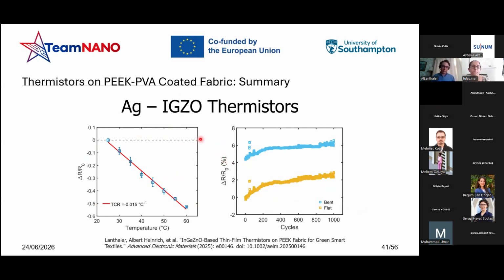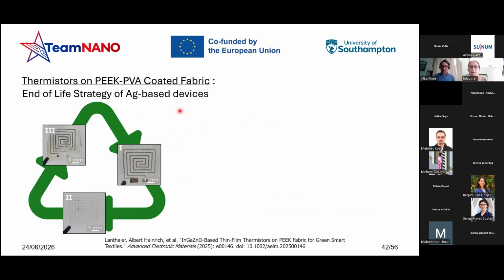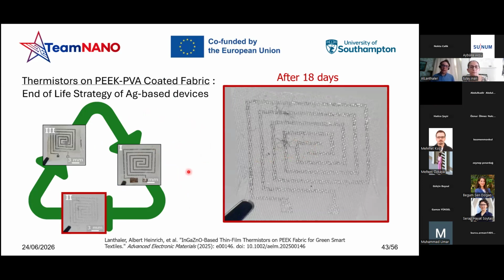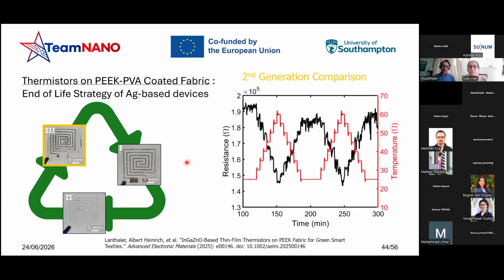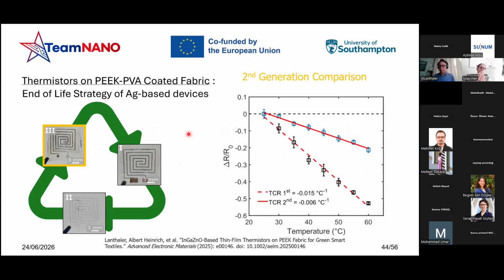What about the recyclability then? Well, since the silver IGZO one was the best among the others, we decided to apply a recyclability method, still in water. So starting from the first device, after 18 days in water, we were actually able to fully dissolve the PVA and IGZO layer, and we were able to refabricate the second generation device on the same substrate, and also recalibrate it.